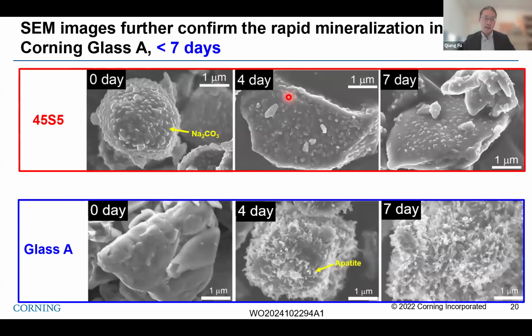We confirmed this with SEM. This image shows for 45S5, after 7 days, you only see sodium carbonate on the surface of the glass. This sodium carbonate is pretty common for 45S5, because the glass starts to corrode in the moisture. For our glass composition, what we found is after 4 days, it starts to form apatite, even if we did not see it in XRD. The apatite already forms on the surface of the glass powder after 4 days. After 7 days, you see more crystals, and you also see them grow much better in morphology, which means the crystals definitely start to develop with a longer time in artificial saliva.